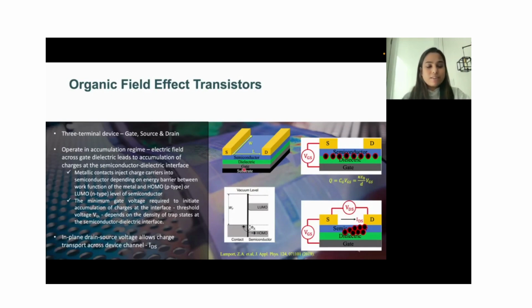However, going back to the presentation, unlike its inorganic counterpart, organic field effect transistors operate in what is known as the accumulation regime, where the application of a perpendicular gate source voltage leads to the accumulation of charges at the semiconductor dielectric interface, as you can see in this image, which is heavily dependent on the energy barrier between the work function of the metallic contacts, as you can see here, as well as the HOMO or LUMO level of the semiconductor, depending on whether the semiconductor used is P-type or N-type.